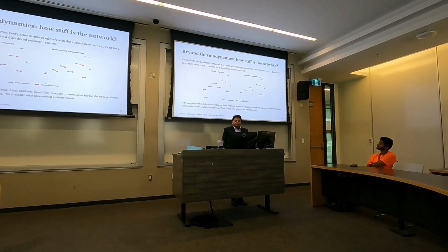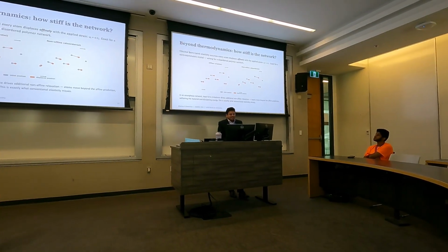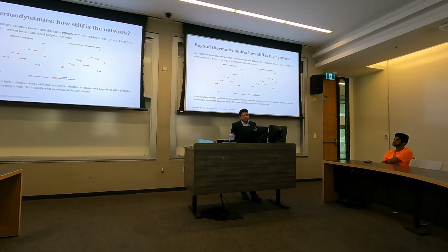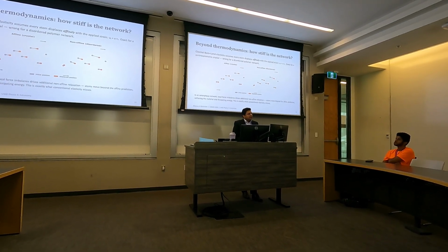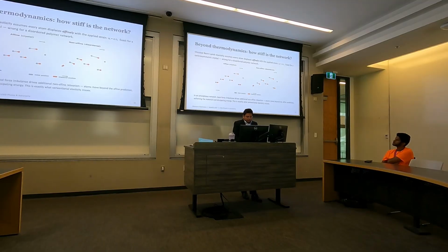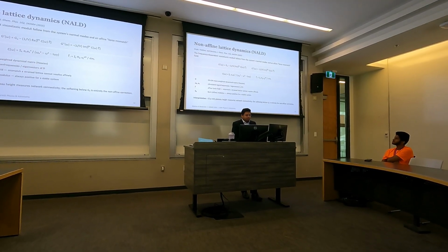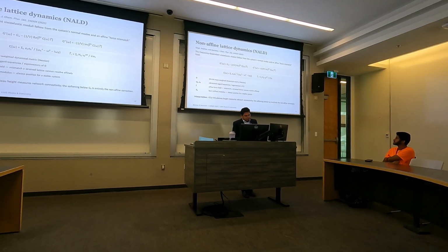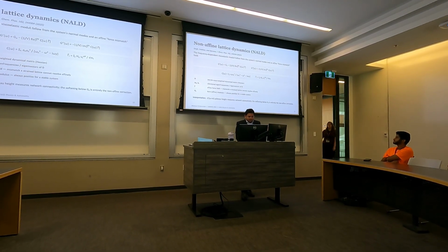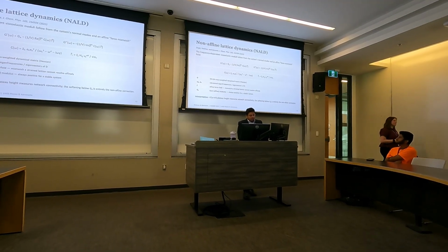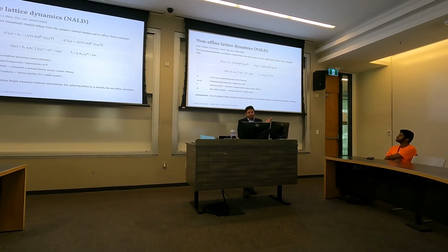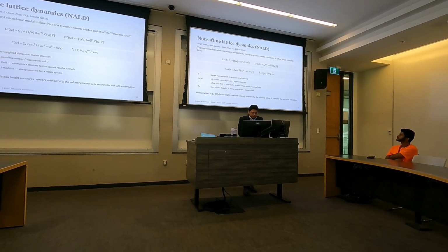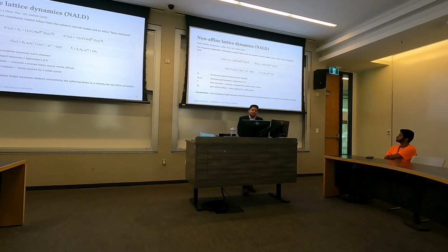So we used something called the non-affine lattice dynamic approach, which was proposed by Professor Zaccone recently, actually in 2025, and that's the one we are going to go with in this case particularly. And what is this non-affine lattice dynamic approach? It gives us a full spectrum of storage and loss modulus, G prime and G double prime, which directly comes from the system's vibrational modes. There is no shear simulation needed in this case.